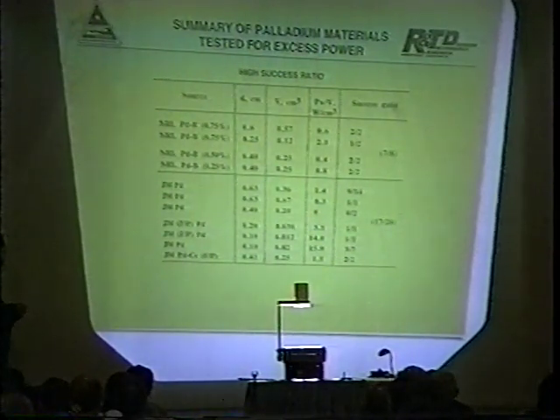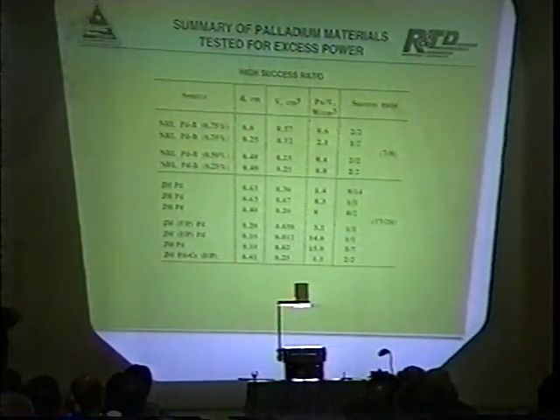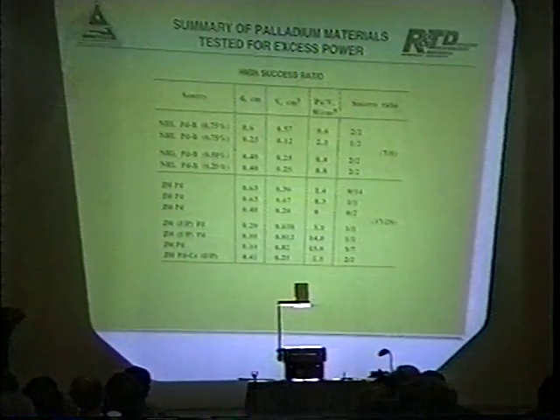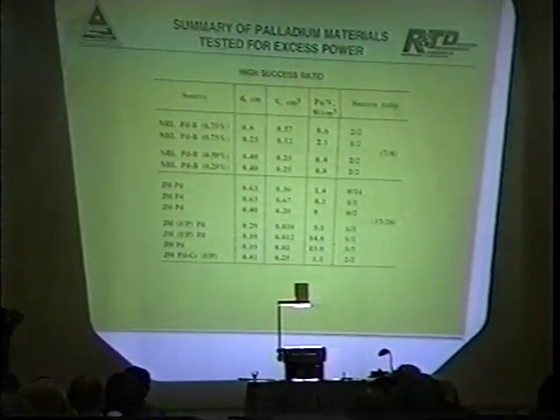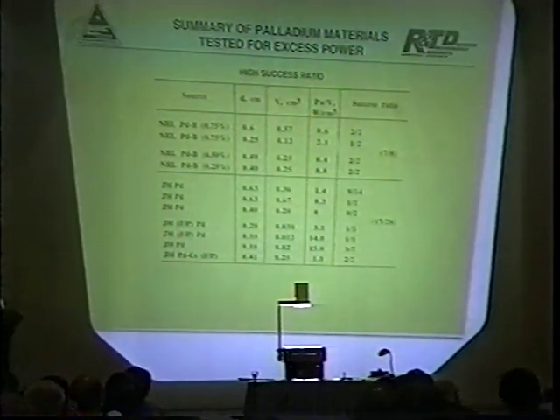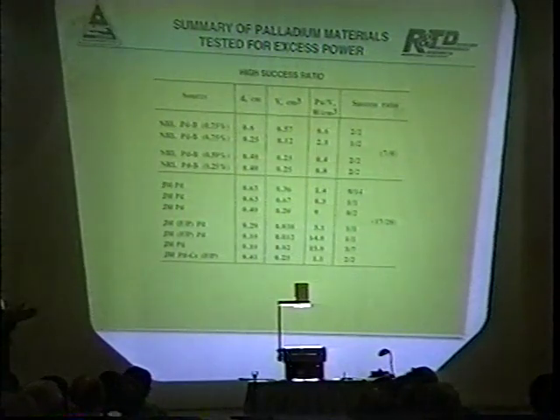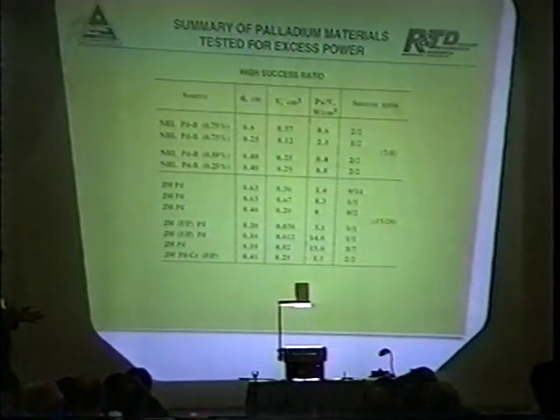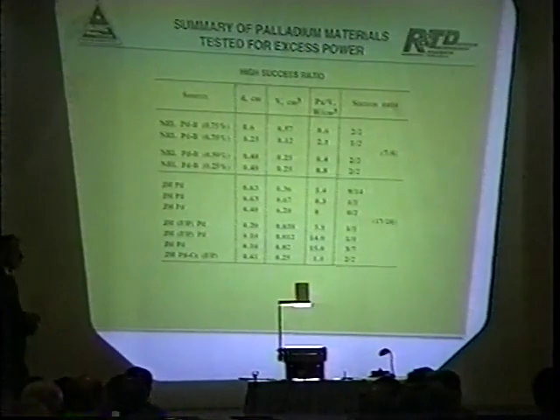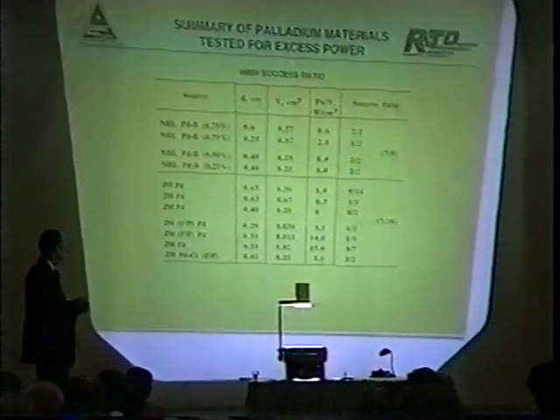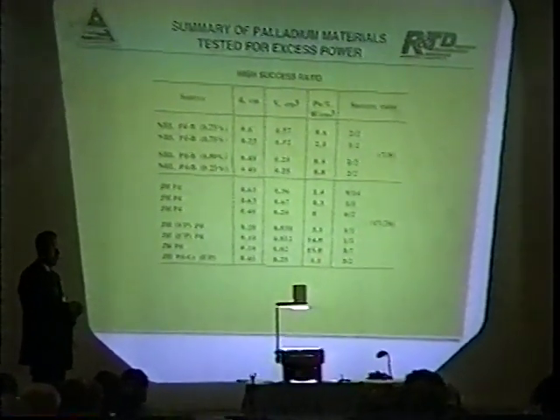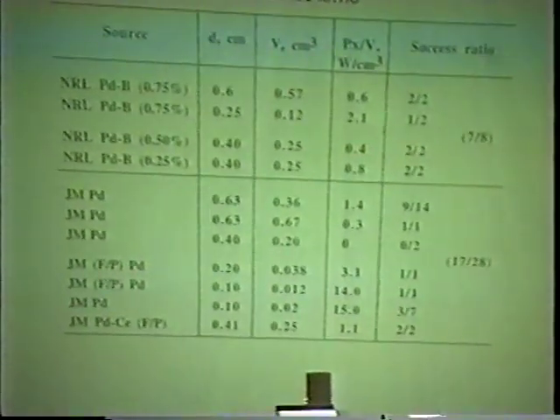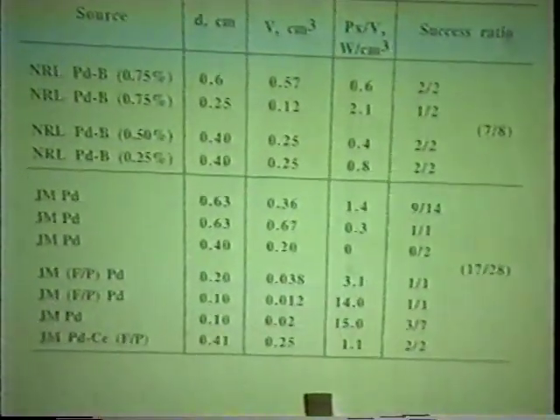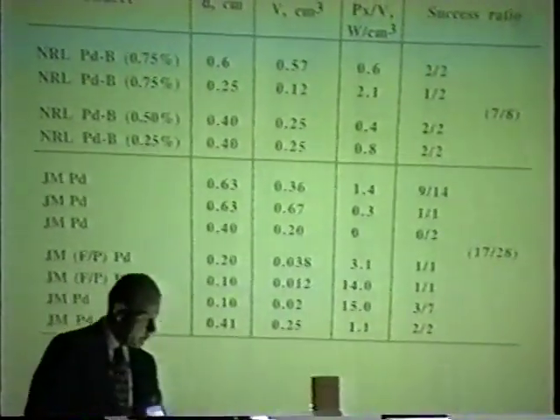The next successful grouping is Johnson-Matthey materials. Out of this group of material, we have 17 out of 28 experiments produce excess heat. So the question is, how could this grouping take place by chance? If we were making calorimetric errors and random errors, you would not expect to find this type of grouping. This shows that the palladium material is a very critical factor in these experiments. If you have good material, you get pretty good success rates for excess heat.